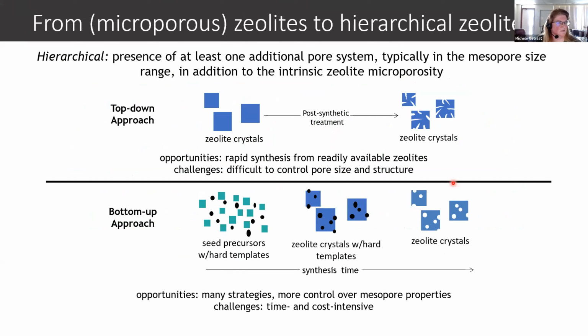In general, they can be classified in 2 different approaches. One of them is a top-down approach, in which you take existing zeolite crystals, you do some type of post-synthetic treatment to etch away, leach out materials, or otherwise degrade the zeolite crystal to be able to add in new pore structures. Some of the opportunities for these materials include a pretty rapid synthesis, because you're starting from already made zeolites and zeolites that are already made at an industrially relevant scale. But some of the challenges include it's pretty difficult to control the pore size and the structure of these materials because it's not as precise as some of the other mechanisms to be able to produce these hierarchical pore structures.